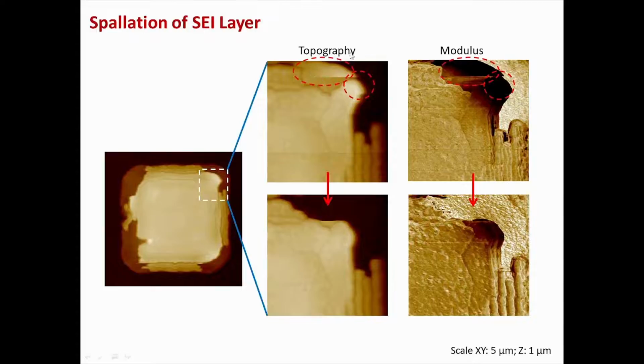So what you could see is that in the topography and modulus channels, the sites which are going to be delaminated or spalled off later during the cycling have a very small modulus. That is, when we are imaging the electrode, they are not very well attached to the underlying silicon, so they come off. If you see the first two images and the later two images, part of the SEI has already spalled off, which can be clearly seen through this AFM technique.